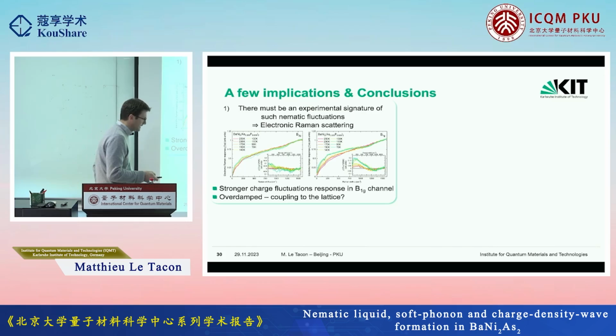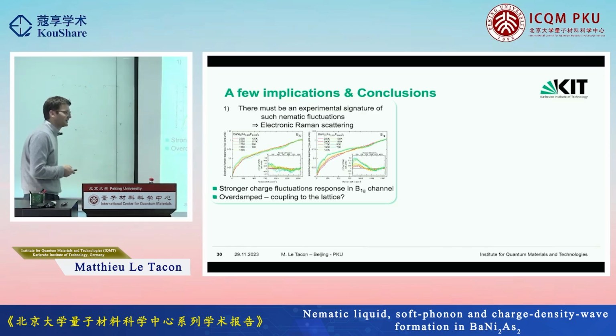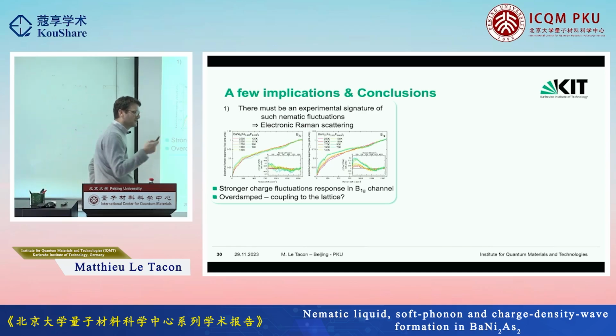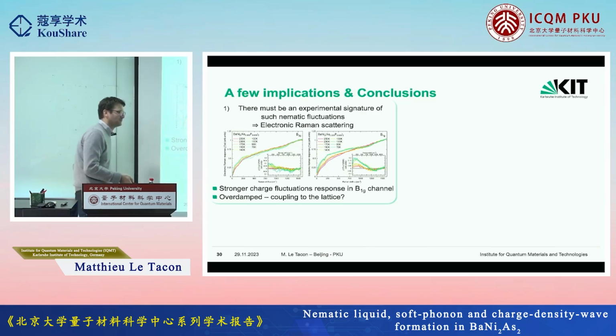But it essentially indicates that those fluctuations are overdamped and suggests that they are indeed coupled to something, very likely the lattice. The second prediction or postdiction, which is quite interesting here, was a prediction on data that we already had but that they hadn't seen. So it's a pre-postdiction.